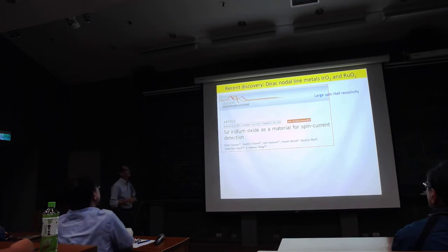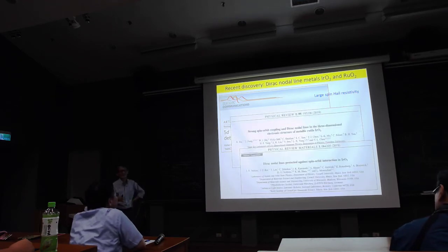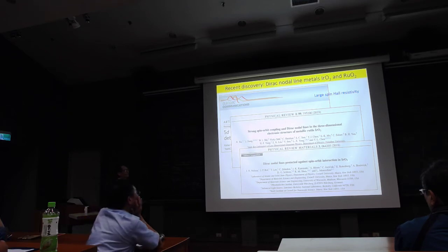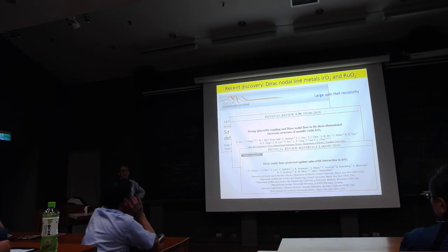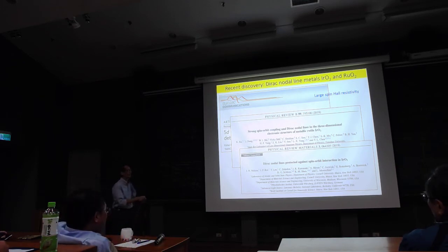And what I want to say is that until the last few years, people have not talked much about topological properties. And in 2013, people found that these two materials actually have a large spin Hall resistivity. The reason for that, this is what they say, I just quote what they say, is that the large or unusual spin Hall resistivity is actually caused by the topological property. They have evidence demonstrating that this material actually is a Dirac nodal line material. So my question is, so far I don't know whether this helps stabilize the orbital two-channel Kondo effect or not. I don't know, but somehow it happened. Just last year they realized that this is a Dirac nodal line material.